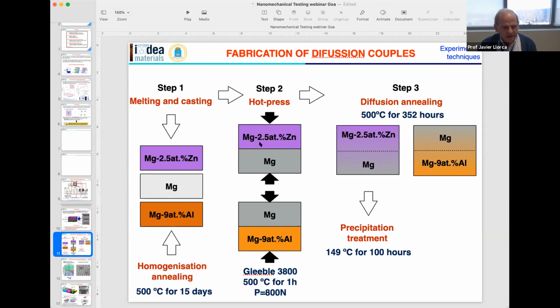And after you have created this diffusion region with plastic deformation, then you go to step 3, that is the diffusion annealing treatment, 500 degrees for 352 hours. And then you create this region where you have a gradient in composition from pure magnesium to magnesium 2.5 atomic percent zinc, or in this case, from pure magnesium to magnesium 9 atomic percent aluminum. And you have here many grains with different orientations and with different compositions.